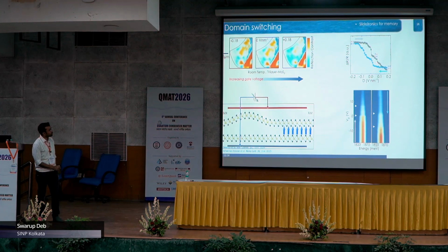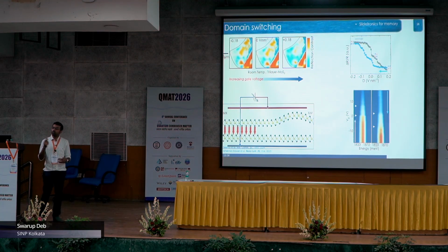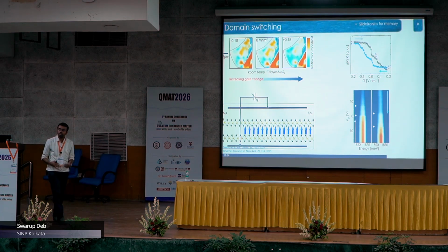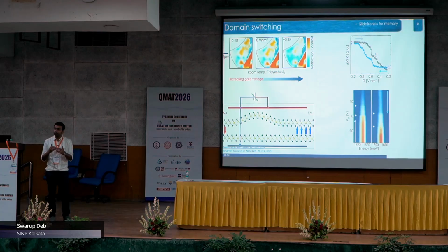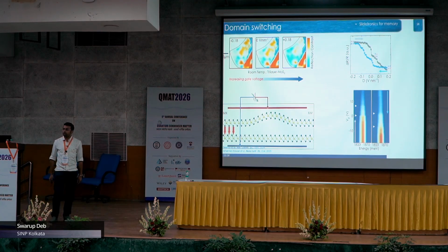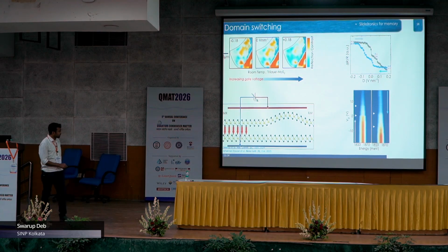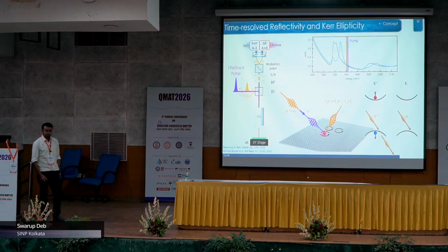And we have one more jump, so interface 1, interface 2, and when you come back, you again have interface 2 and interface 1. But of course, we have seen that if you keep on doing this experiment, these sharp transitions keep on vanishing. They do not really stay sharp anymore, and they smear out. So we believe that these domain walls start getting pinned to local defects and all the contaminations that are there. So this is about steady state spectroscopy.